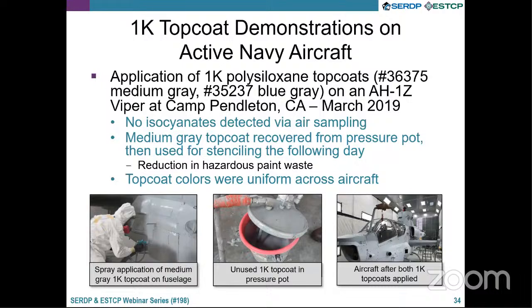The photo in the bottom left shows an artisan applying the medium gray top coat over a chromated primer. One of the initial things we did during this application was have the industrial hygiene office take air samples to prove there were no isocyanates in the coating. The results came back showing no isocyanates detected.